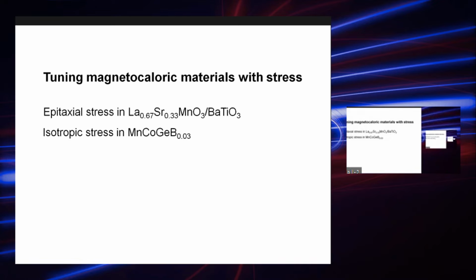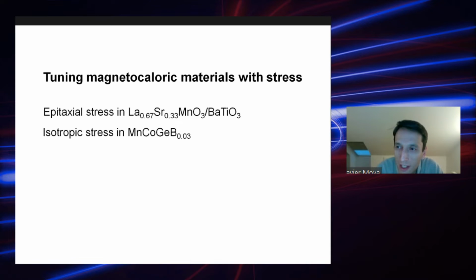So today I'm going to be talking about two different sets of materials. The two of them are, well, especially the first one is a classical magnetocaloric material. It's a manganite of lanthanum strontium manganese oxide, so this one here, which you can actually grow on top of a ferroelectric substrate because these two materials are perovskites, so they have the same structure. So it's very easy to grow them one on top of each other. And when you do that, basically you have a combination of a magnetic material with a strong structural coupling and a ferroelectric material. So you can expect to have magnetoelectric effect. So this is an example of an extrinsic multiferroic material that is strain-coupled.